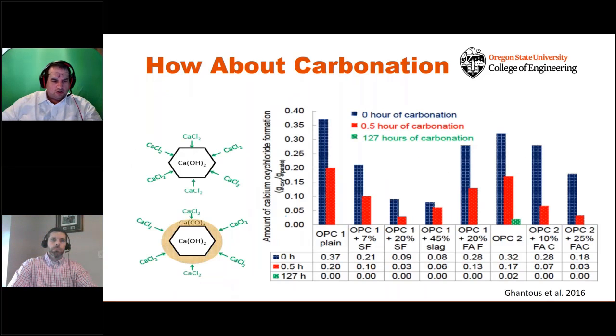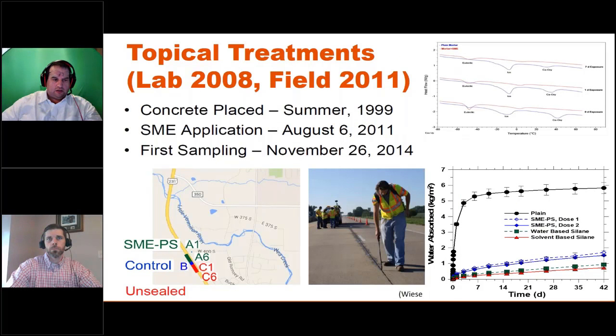The other thing that we noticed that seems to work fairly well in these systems to reduce the potential for damage, and this is a little counterintuitive, is if you actually get the system to carbonate a little bit. You get CO2 to react, it preferentially reacts with the calcium hydroxide and forms like a little candy coating. So you can think of this a little bit as like an M&M shell, can protect it from calcium oxychloride.